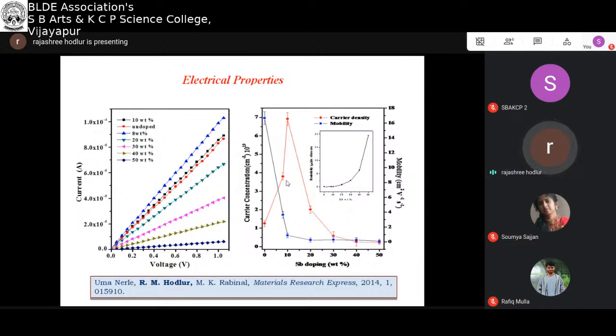So we studied the electrical properties of these films. Our interest was mainly focused on the SPR properties, but in order to confirm their conductivity and other electrical parameters like carrier concentration and mobility with respect to the doping concentration, we carried out the IV measurements, and using the Hall effect setup, we determined the carrier concentration and mobility of these thin films. So you can see here clearly with the increase in the doping concentration how the resistance can be tuned. Not only the resistance, even the carrier concentration and the mobility can be tuned for these films.